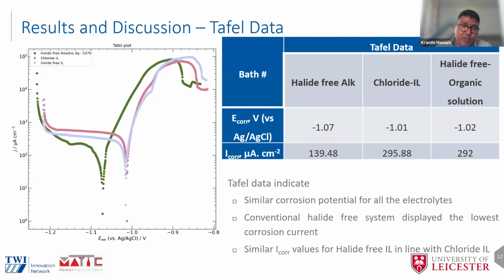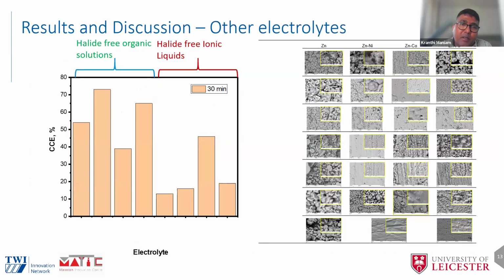With this motivation, I tried to develop different organic solutions. I thought organic solutions would really perform better, which was the motivation why I performed the initial study using the standard benchmarks, that is the alkaline aqueous as well as the chloride-based deep eutectic solvents. So I could figure out that a halide-free organic solution can perform better. You can see on the left, when you compare the cathodic current efficiencies, the organic solutions are really performing better than the halide-free ionic liquids.